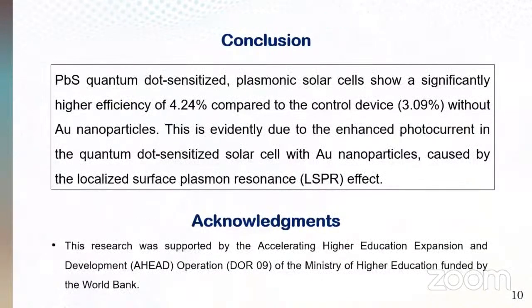QDSSC with gold nanoparticle photoanode shows an efficiency of 4.24% with a higher short circuit current density. The enhancement in overall power conversion efficiency of the PbS QDSSC with gold nanoparticles relative to the device without gold nanoparticles is about 37%, and the current density enhancement is about 35%. This is evidently due to the enhanced photocurrent in the QDSSC with gold nanoparticles caused by the localized surface plasmon resonance effect.